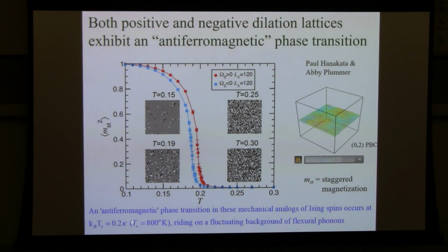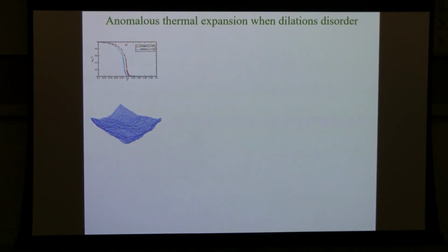There seems to be an antiferromagnetic phase transition riding on top of the background of these flexural phonons. So one question is, does this change the Ising phase transition that Onsager found for a rigid, incompressible Ising model? And we think it probably does. So here in this staggered magnetization is where we think the Tc is. There's a specific heat-like singularity there.